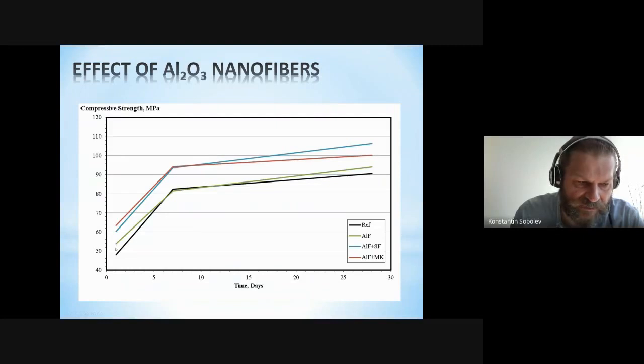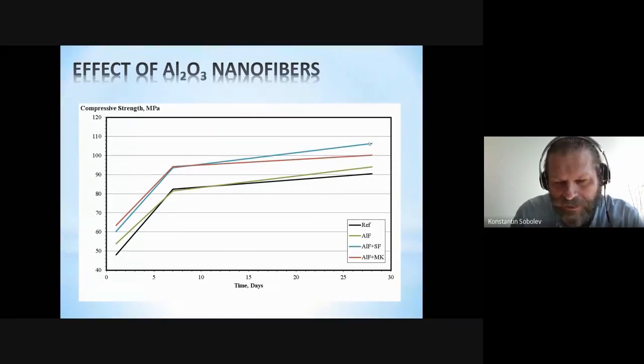Yes, we had some improvement of early strength, but also we had some improvement of 28-day strength. But when we discussed using the fibers, we realized a better cementitious matrix is required. So using small quantities of silica fume or metakaolin, usually about 1%, is extremely useful for proper incorporation of nanoalumina fibers.